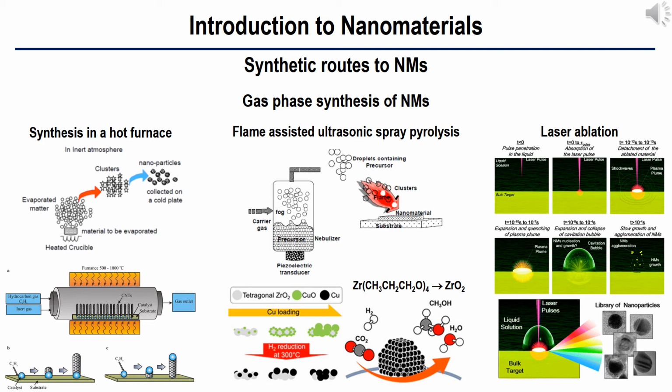Low-pressure flames have been extensively used by aerosol scientists to study particle formation in the flame. A key for the formation of nanoparticles with narrow size distributions is the exact control of the flame in order to obtain a flat flame front. Under these conditions, the thermal history, that is time and temperature, of each particle formed is identical and narrow distributions result. However, due to the oxidative atmosphere in the flame, this synthesis process is limited to the formation of oxides in the reactor zone.